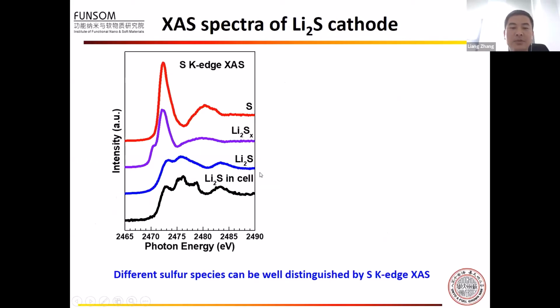Before the in-situ experiment, we first measure the reference spectra for different kinds of sulfur species. We measure elemental sulfur, lithium sulfide, and lithium polysulfide, and we also measure the lithium sulfide in the in-situ cell. We can clearly see that for the lithium polysulfide, the purple line, besides the main feature, we can see a pre-edge feature here, and the pre-edge feature is related to the sulfur bonded with lithium in the polysulfide.